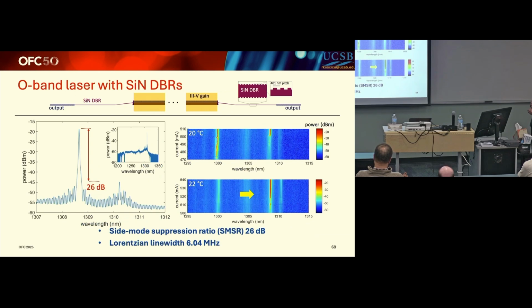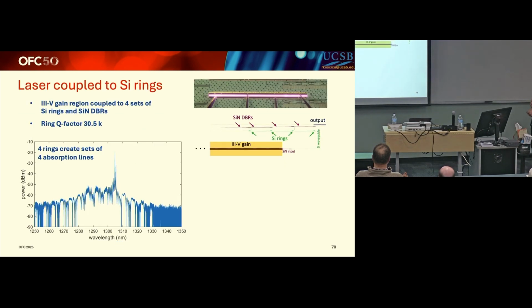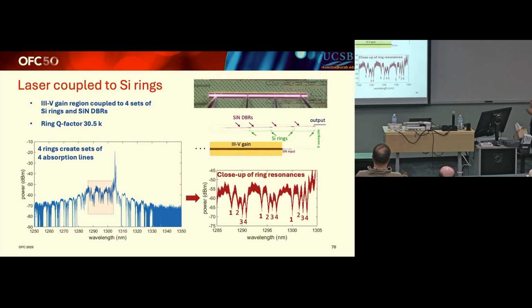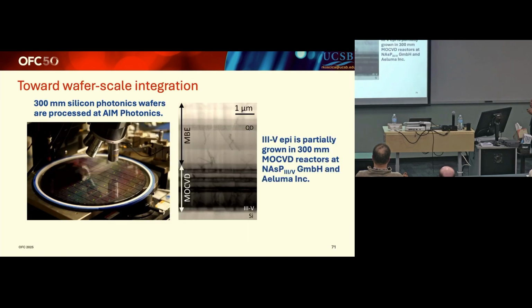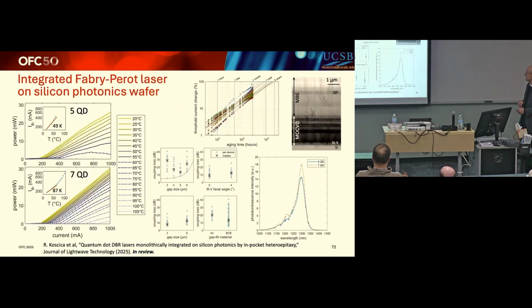So now we're making DBR lasers where the gain region is coupled to DBRs in the silicon nitride, just to say okay, we do get enough coupling to make an external cavity laser. And we couple it with modulators then, and that's shown here - these are coupled to 4 modulator arrays. Again, AIM is developing this, so everything is now on 300 millimeter wafers. So again, it's not really ready for prime time yet, but it's getting a lot closer.